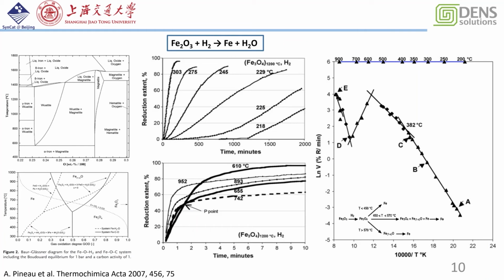Based on the phase diagram, we can show here iron oxide reduction by CO and hydrogen to form metallic iron. The information looks very simple. Even at 300 degrees, using pure hydrogen, we can get complete reduction from iron oxide, hematite, to metallic iron. But somehow, if you look at the reality here, when we use different temperatures from 200 degrees to 800 to almost 1000 degrees, we can see that the reduction of the iron oxide to iron is very difficult.